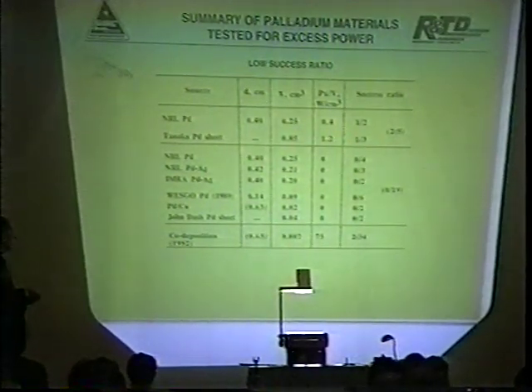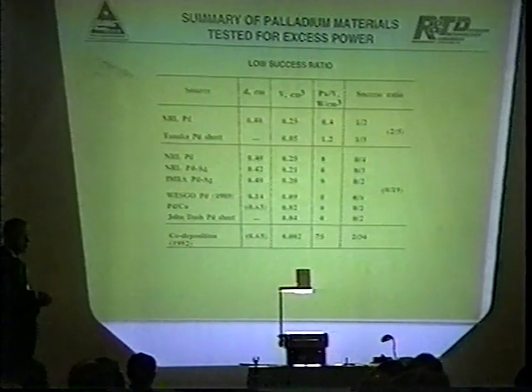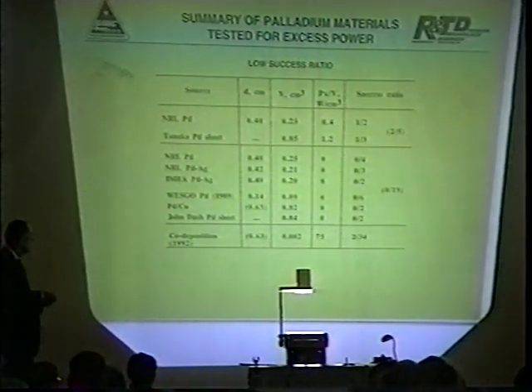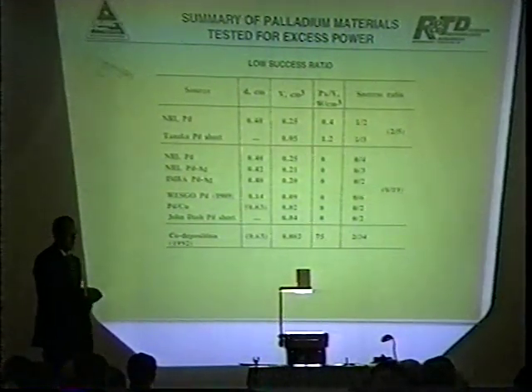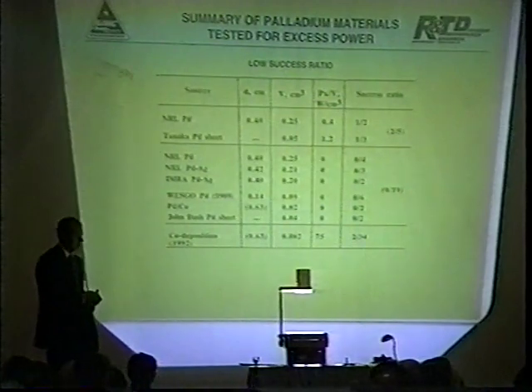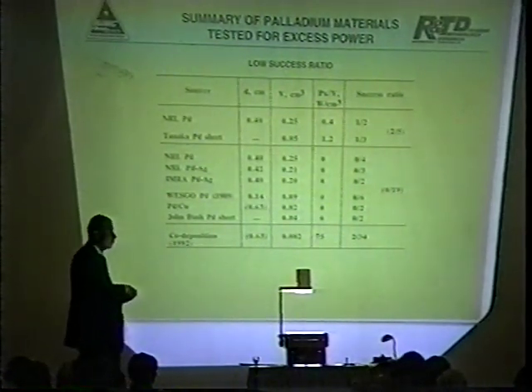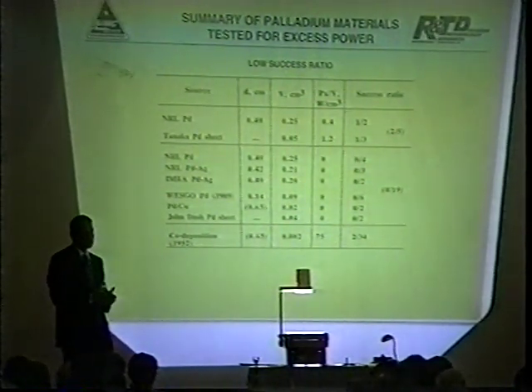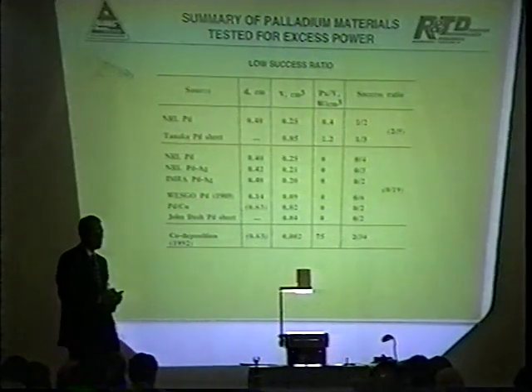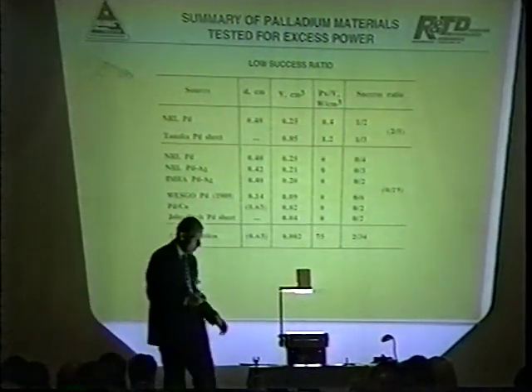And this was a very small volume, so we would not have been able to detect it, even if the excess heat had been there, unless we were very high. We would have had to have 75 watts per cubic centimeter for this small amount of palladium in order to detect any excess heat. So I still think the co-deposition method is a valid method that should be further investigated. But you need a more sensitive calorimeter than ours in order to do that.